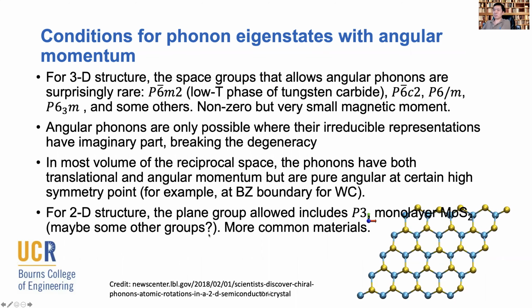If you look at 2D structures like the one I'm showing in the lower right corner, it turns out, yes, you can do that. And this is actually one of the eigenmodes for phonons. It does carry angular momentum, you can clearly see. And we can actually achieve the same thing with 3D structures. We can only do it for certain limited space groups, with broken center inversion symmetry, but it can be done. Those phonons are going to have eigenvectors that have an imaginary part, which is basically a phase factor.